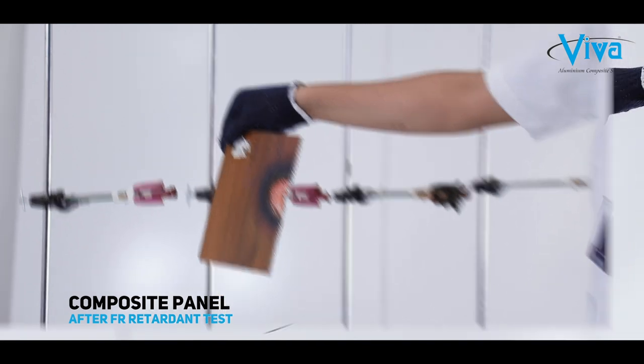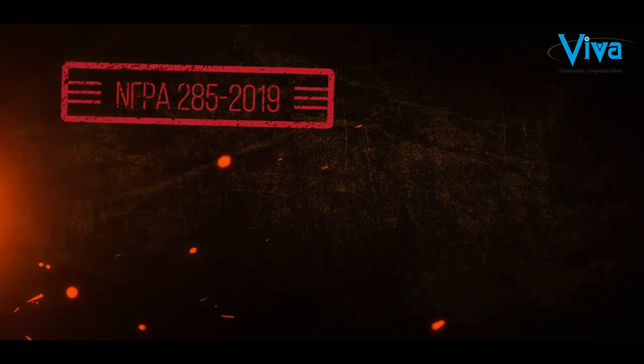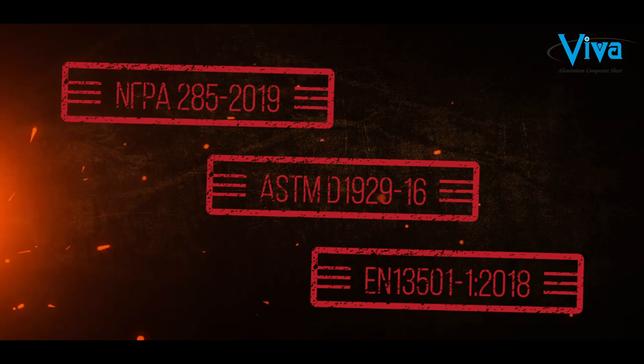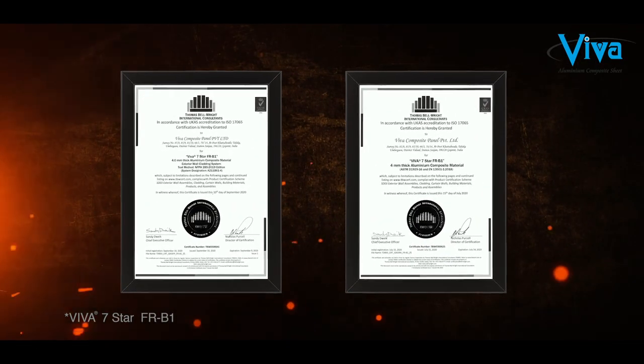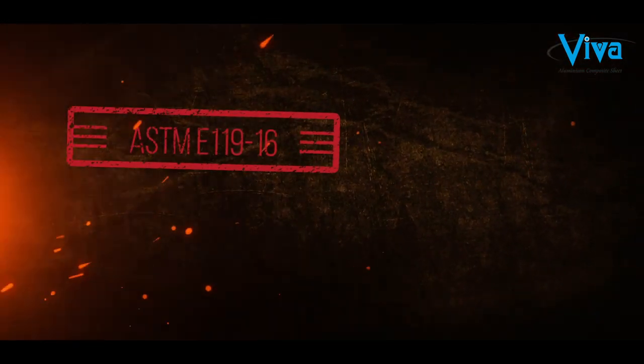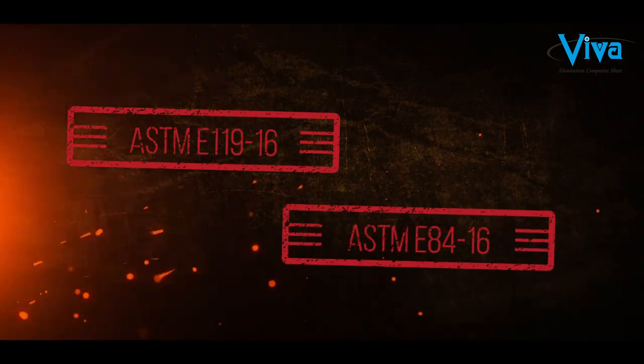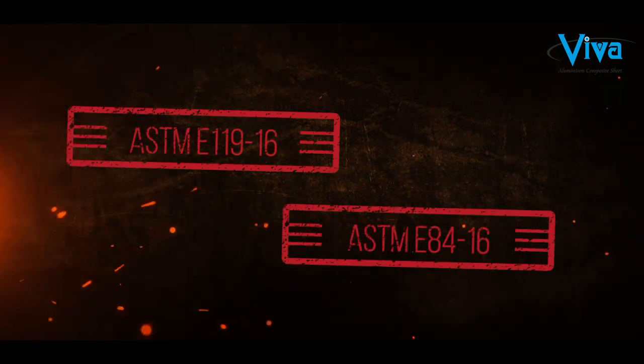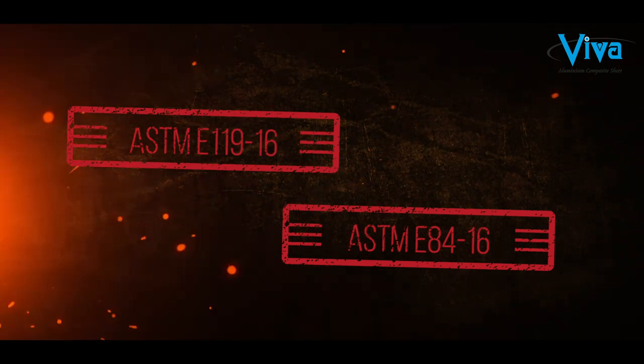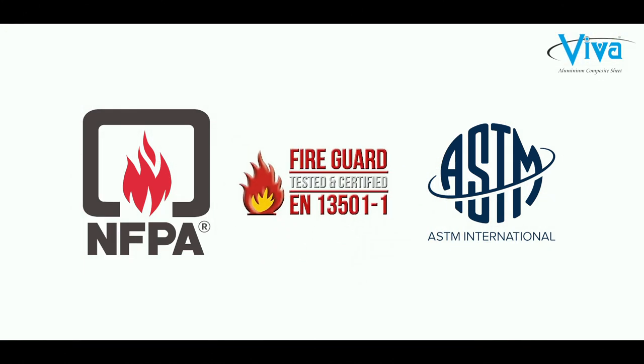Viva Fire Retardant Composite Panels are certified as a complete system test under NFPA 285, ASTM D1929 and EN13501, tested and certified by Thomas Bell Wright International Consultant. They also passed ASTM E119 for 2 hours of fire safety, with ASTM E84 for zero flame spread and zero smoke developed. These international certifications define the safety standards and certify 100% fire retardant products.